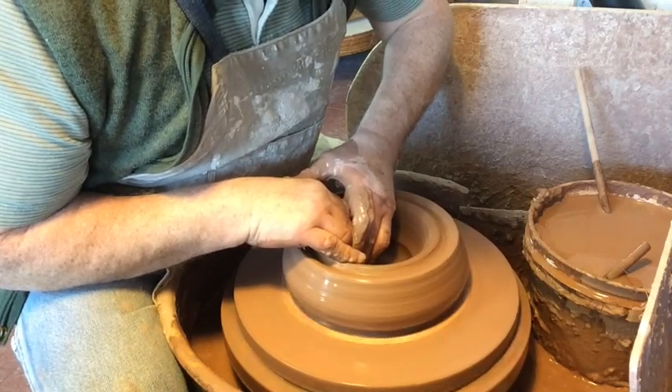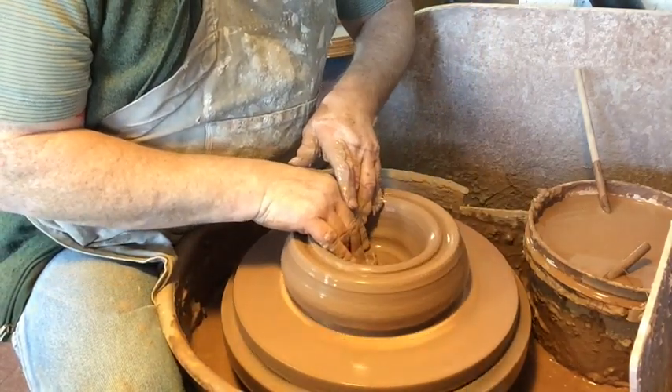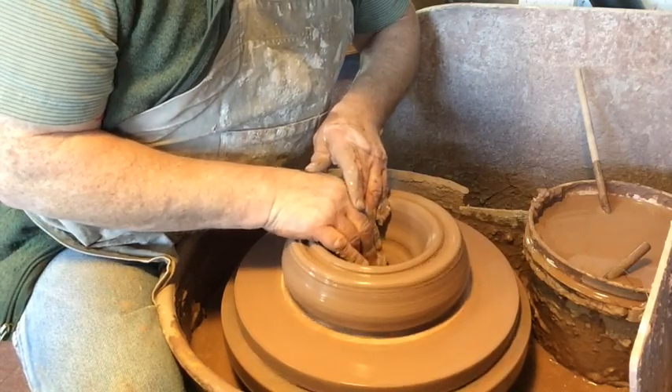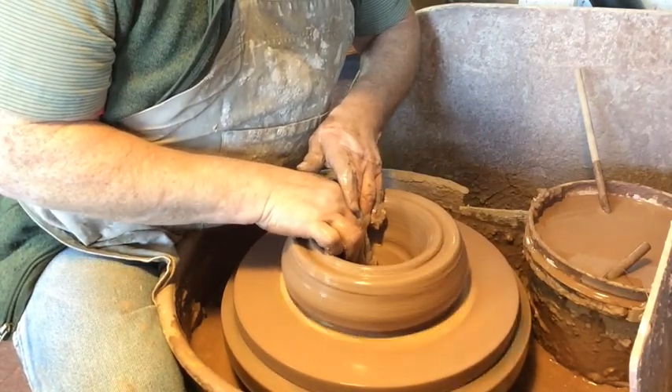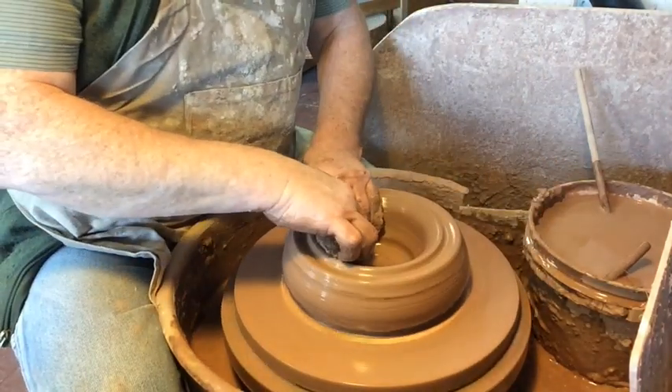The reason I'm doing that is I'm hoping I'll be able to double dip Randy's red with the other glazes. But the other glazes are like cone 6, and if I go up a bit higher than cone 6 with the turquoise I have and also the blue, you tend to get little blister bubbles, so they don't want to go any higher.